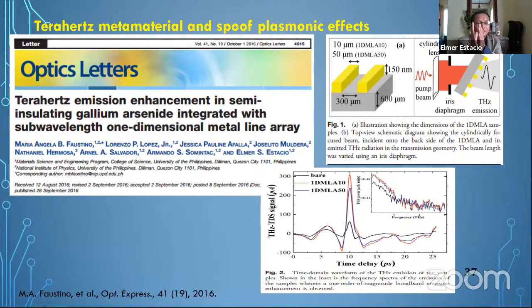And if we are able to develop conducting materials or arrays of metals having spacings pretty close to the wavelengths, we may be able to observe some spoof plasmonic effects that are normally observed in the microwave or even in the visible region. And we were able to do so. A few years ago, we were able to demonstrate a strong enhancement of terahertz radiation in semiconductors if we fabricate an array of closely spaced gold lines in a gallium arsenide layer. And we published this work on our terahertz emission enhancement in a metal line array in Optics Express.